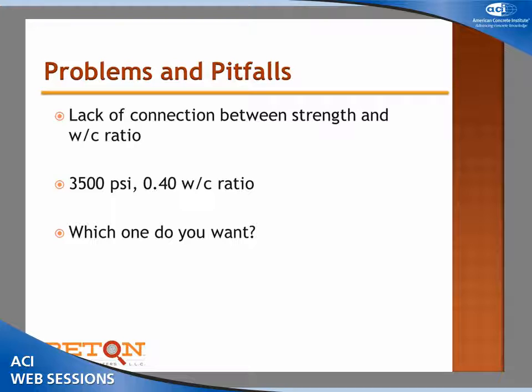If you go outside and walk a block from the hotel, you can see Target's headquarters. And so the Target people call me up and say, we don't like using your concrete. So why not? Well, the strength is really, really high. It's like 6,000 or 7,000 psi, 28 days. Well, it's specified to be 3,500. It sure is. And it's specified to be a 0.40 water to cement ratio. And since the 0.40 gives me 7,000, what do you want? Well, I want a 0.40, 3,500 psi concrete.